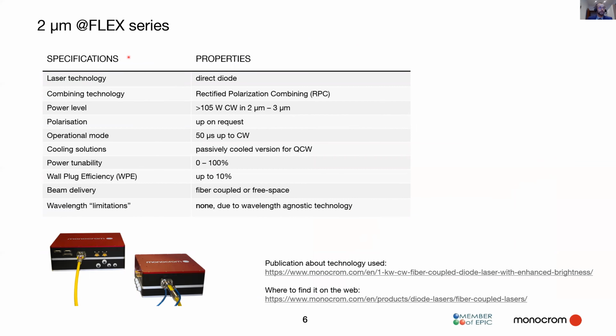Our @FLEX series are direct diode-based systems, which are using a combination technology called rectified polarization beam combining. This allows us to combine several laser bars while maintaining the beam properties of one single laser bar, meaning that we have the spatial and spectral properties of one single laser bar while we are increasing the brightness by adding up 2, 4, or 8 times the power of the laser bars. So this enables us to reach up to 105 watts CW in the region of 2 to 3 micron.